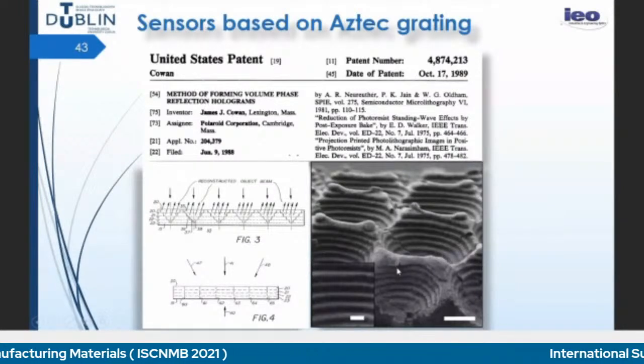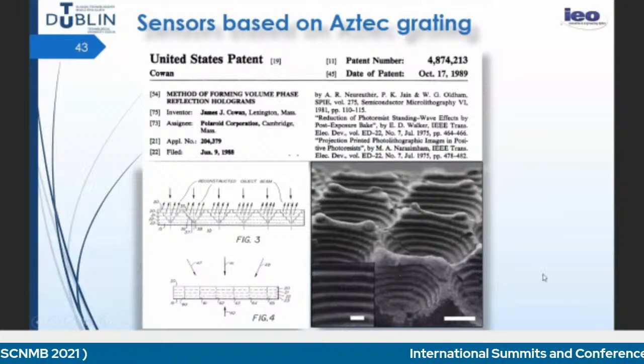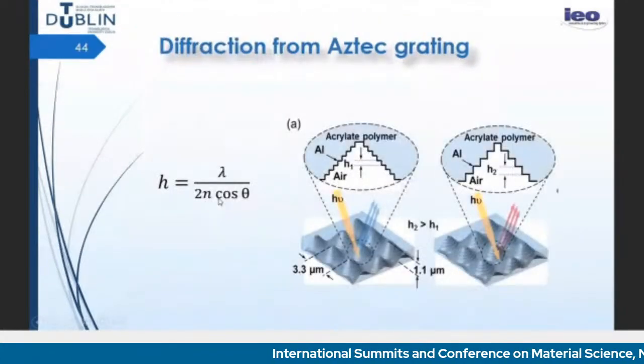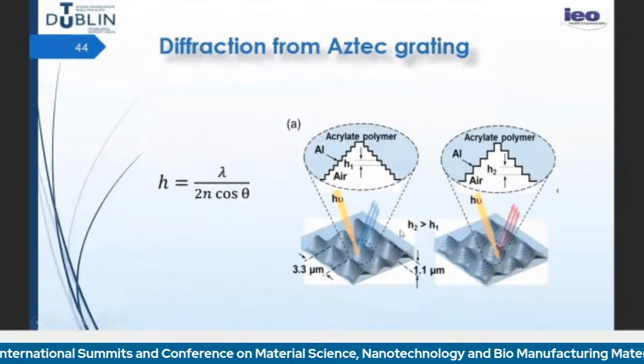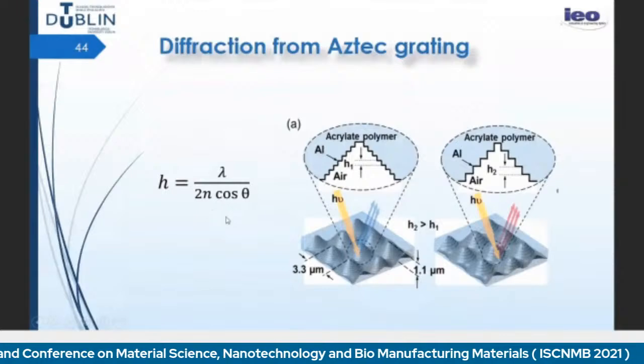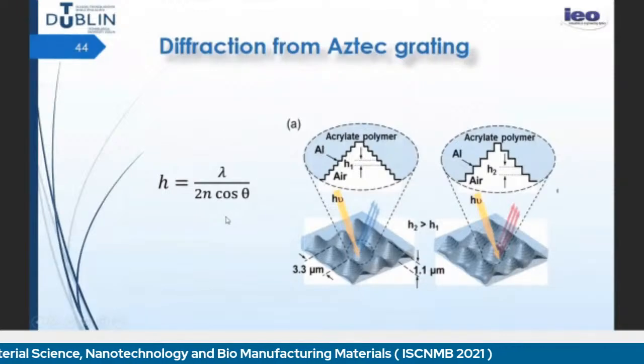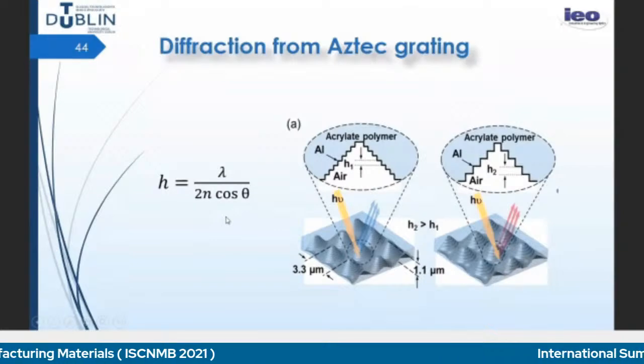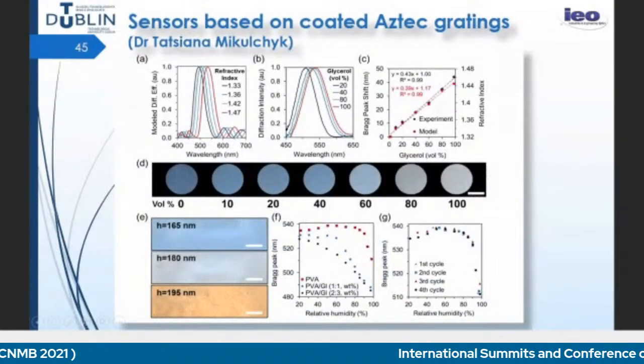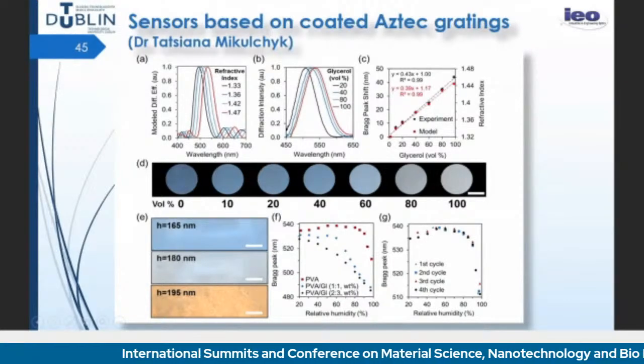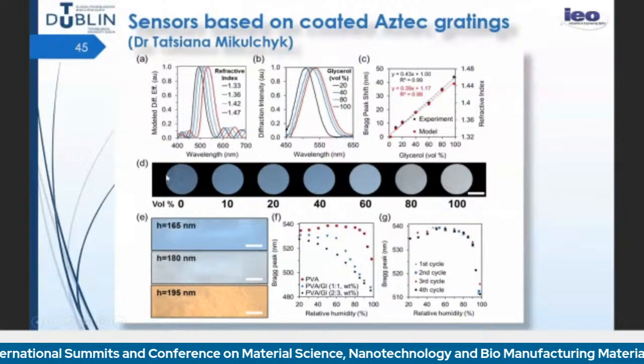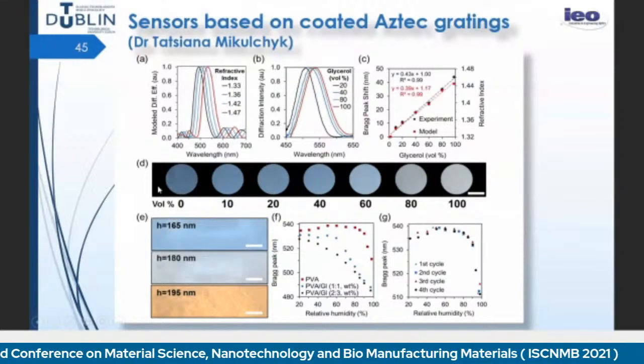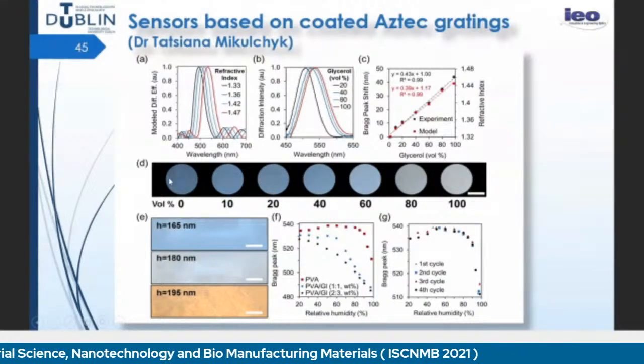Then these gratings are coated with different coatings, and the wavelength of the reflected light depends on the step size and also on the refractive index of the coating. So if the refractive index changes, then the wavelength and the color change. And these are some results. These are theoretical results, how the refractive index change leads to a shift in the reflected wavelength. These are results from glycerol in water, how when you increase the glycerol, the refractive index of the coating changes, and then the appearance changes.